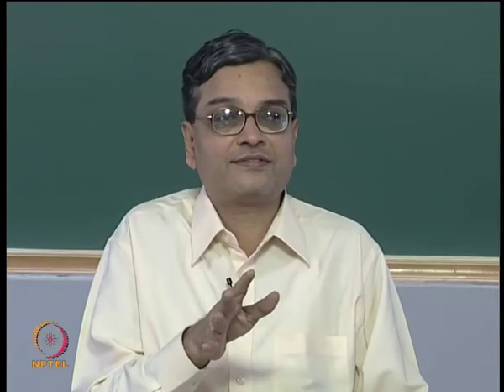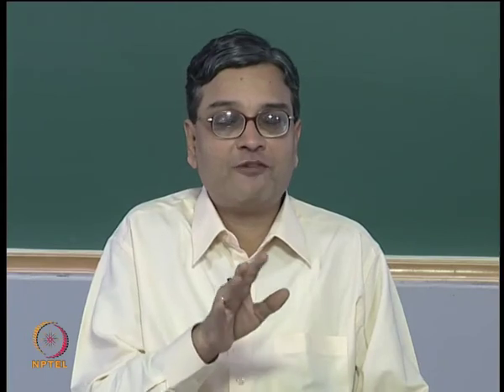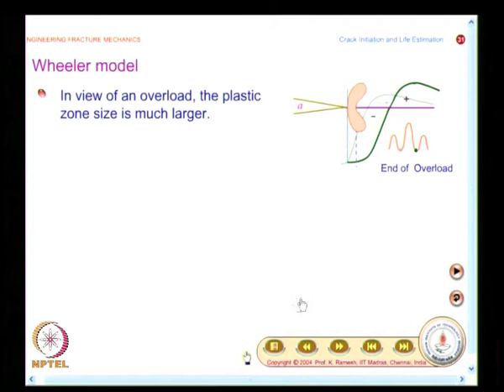Here again, we will go back to Paris law and modify it. The beauty of Paris law is he got the kernel, others have come and modified it suitably to take into account crack closure. They simply said instead of delta K, use delta K effective. In the case of retarded crack growth, we will have a different type of model, and we would also have pictures for each one of these cases. We will also see them.